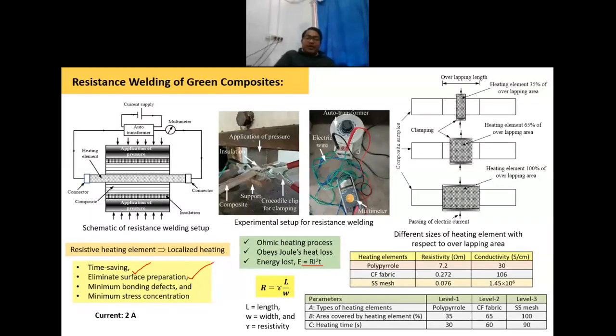Then there are minimum bonding defects, because you are not creating any holes and you are not applying any adhesives. When you do the testing, you will observe different types of defects, and you will observe the minimum defects compared with the mechanical and adhesive joints. Stress concentration is also minimum because you are not creating any hole.